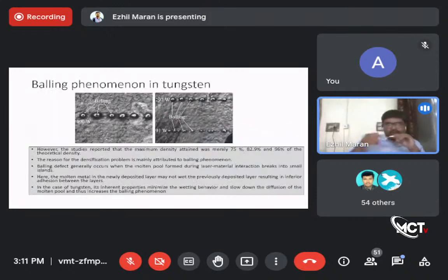When tungsten is processed by selective laser melting, the main issue is balling. That is the phenomenon. The molten liquid-like ball-like structure is deposited on the layers. Balling generally occurs when the molten pool formed during laser material interaction breaks into small islands. This ball-shaped liquid is deposited on the surface. So when the next layer is coated on this structure, which contains balling, layer to layer adhesion may not be proper. That is an issue.